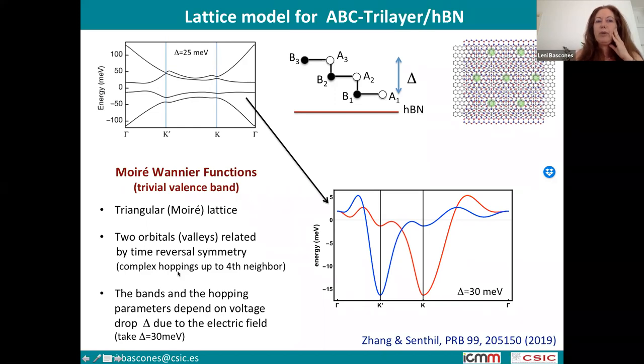So the Wannier functions, or the model that one can build, has sizable hoppings up to at least fourth neighbor. And then the hoppings in the two valleys are related by time reversal symmetry, and they are complex. So you can see here, I'm plotting the two valleys. One is the blue one and the other one is the red. So with the field, we modify the bands, and then we are going to choose one of the valleys.